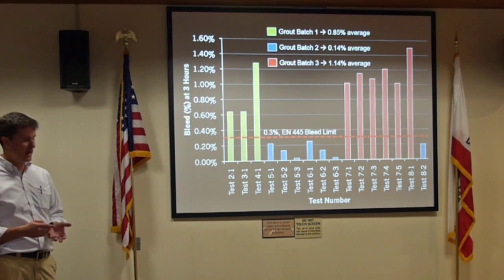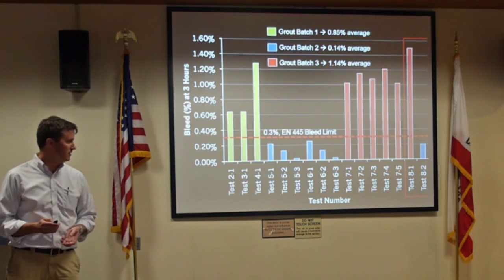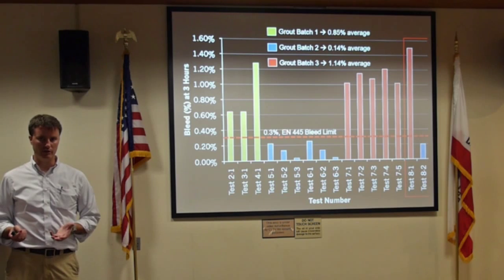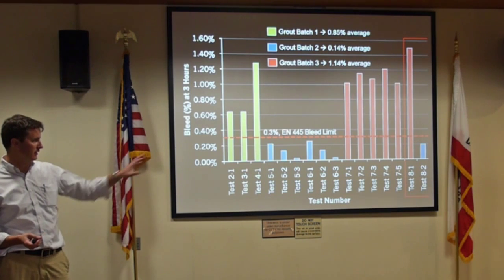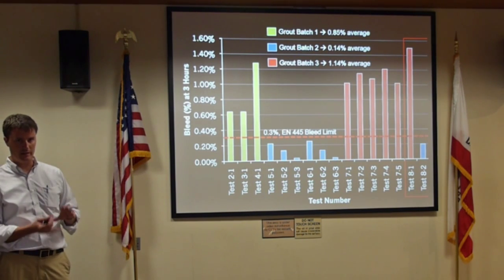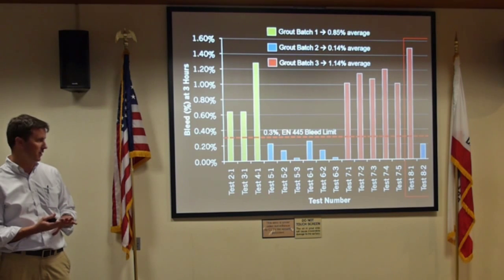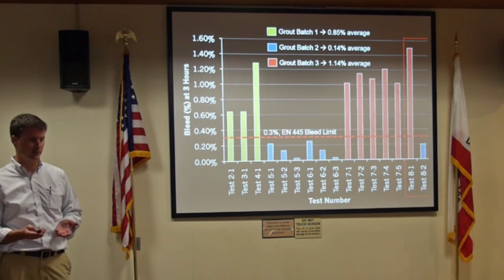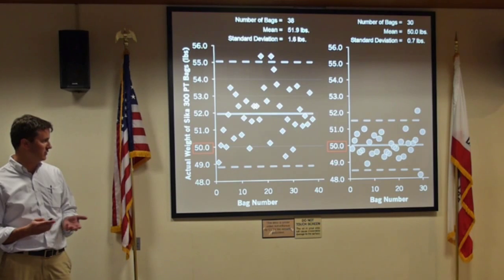Basically we ended up looking at different batches out of the plant, and what we found was that depending on which batch, you got very different results. There's series of tests, and the interesting thing there on the right is that those tests were performed same day, same weather, same temperature, same water, etc. But we got two different results depending on which batch you're actually looking at.